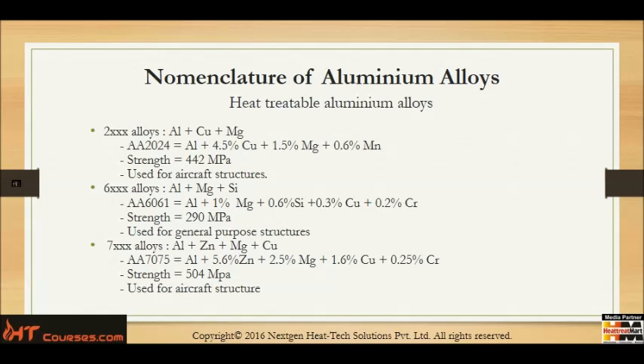Moving to the heat-treatable alloys, we now have 2XXX, which is aluminum plus copper plus magnesium, sometimes identified as AA2024, and that is aluminum plus 4.5% copper plus 1.5% magnesium plus 0.6% manganese. You will notice the tensile strength now really increases quite dramatically to 442 megapascals. This alloy is used principally in aircraft structures.